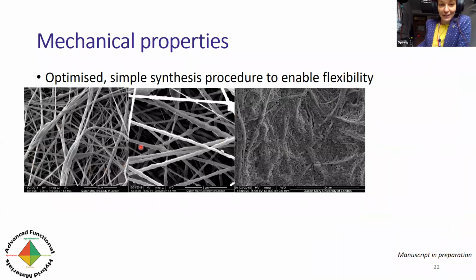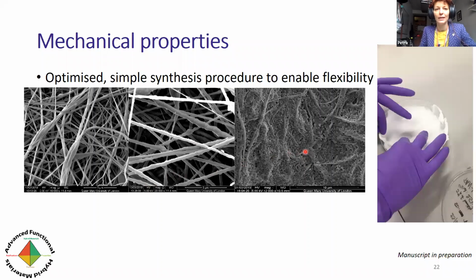And so first and foremost, of course, we managed to do it, and that is what's shown here. Here you can see the scanning electron micrograph of just the pure polymer without framework on it. And as we mix the polymer solution with the framework crystallites, we get to this sample. Particularly, maybe the best giveaway is the high charging you get from the non-conducting, insulating framework, which shows that we really managed to very intimately coat the fibers with metal organic frameworks. Furthermore, you can take this fiber mat and immerse it into a metal organic framework reagent solution and carry out the framework formation, and that can really fill the space in between the fibers with metal organic frameworks. So we can really control the density and the tightness of these membranes.